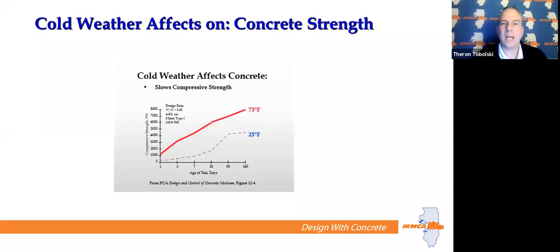How does it affect concrete strength? You can see if you keep your concrete at 73 degrees, this concrete mix reached about, let's just say, 7,000 PSI. If we took that same mix and we kept it at 25 degrees, we didn't protect it, we didn't have warm weather concrete, we only ended up at 3,000 PSI. So it just shows you that you lost 4,000 PSI in your concrete by just not keeping the concrete the right temperature.